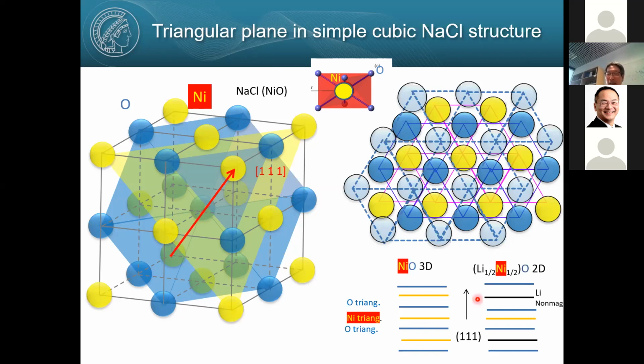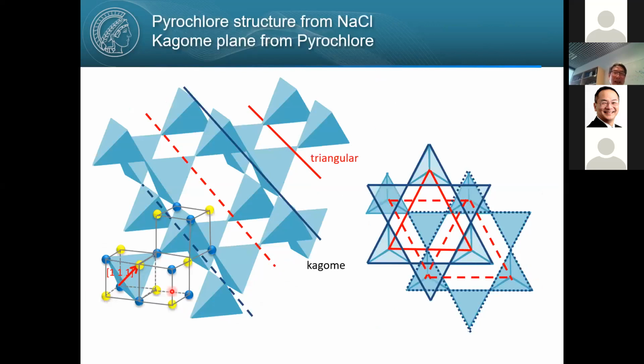But if you replace every second nickel layer with a non-magnetic ion, like lithium, you can isolate the triangular nickel lattice like this. Okay, and make a magnetic 2-dimensional triangular lattice. Okay, or consider again the cubic sodium chloride structure, and those sodium ions, as you can see, form a tetrahedron. And if you take tetrahedra connected by the corner from the sodium chloride lattice, you find the so-called pyrochlore lattice. Okay, so actually the pyrochlore structure is closely related to the sodium chloride structure. So actually it's quite common in nature.